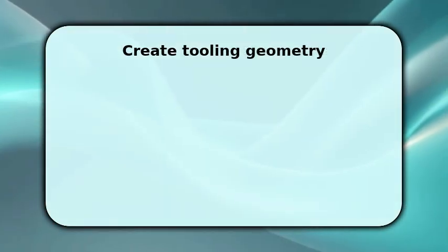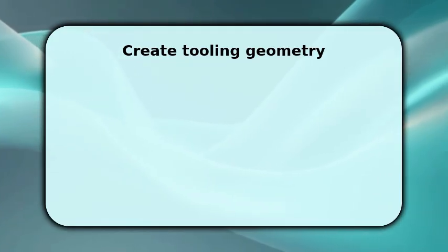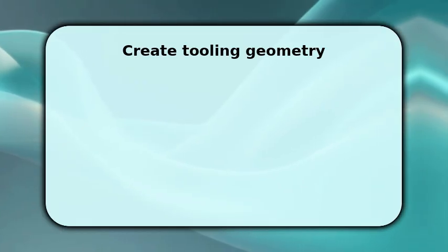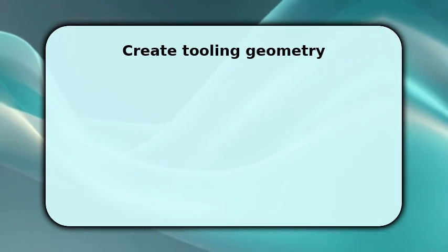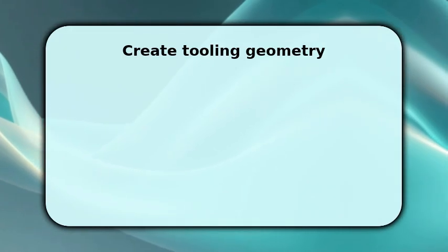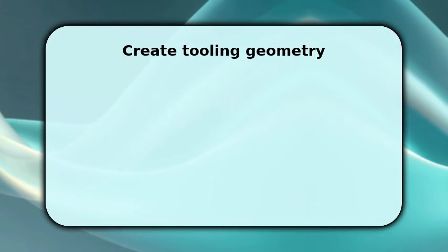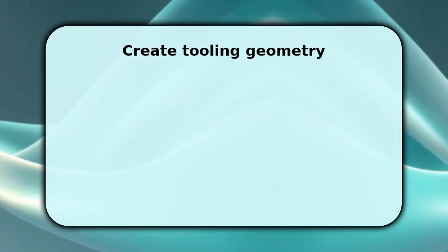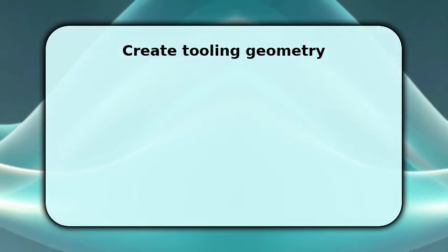You now convert the design into tooling. Use the split tool to cut the model along the parting surface so you get separate core and cavity bodies. Then offset faces to account for shrinkage and machining allowance, for example 1-3% or a fixed 0.5 mm, so cast parts match final specs. Once done, add draft and radiused edges to the mold halves to assist release, and model alignment pins and locating features. These maintain repeatability and simplify assembly of the tooling.